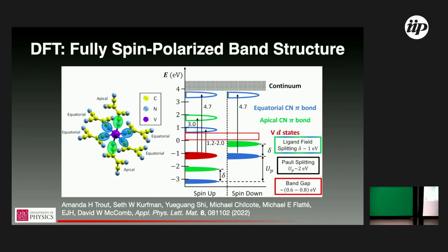This is a spin-resolved density of states, and with apologies to Michael and his crew, I'm picking the cartoon version because it's easier to point at. I'll show the actual calculations in a minute. They actually did do all this work. The first is that it's spin resolved, and matching color to color, these are the 2 pi star orbitals on the TCNE. You can see first there's this Pauli splitting that's huge. It's 2 eV. So that's one of the key interactions that's driving the magnetism and the spin polarization in this system.